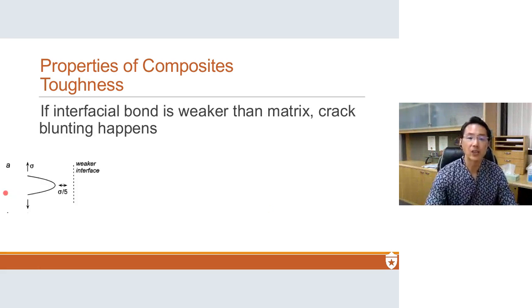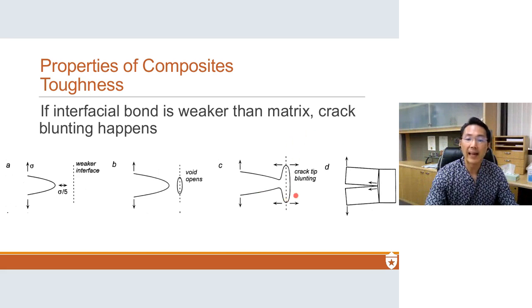So this is a little schematic showing that. There's a crack propagating this way. This is the interface, and the coupling agent is usually weaker than the filler particle. As it approaches, a void starts to open up, just because of the geometry and the stresses. It has to go around the particle, and while not always perpendicular, there's an extreme change in direction. So it literally blunts the crack from going through. The amount of energy required is much higher to go around that, especially if it's perpendicular. If you think about the forces and stresses being directional, you have no y direction of force going this way, and yet now you have to have something like that, and so it blunts the crack.